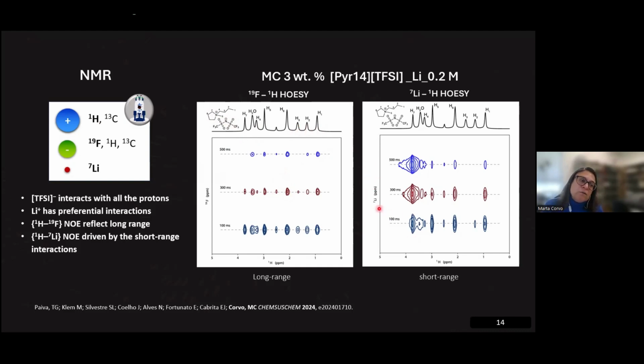And what is interesting is what we see when we look at the lithium-proton behavior, the lithium-proton correlations. Here you really are looking at some correlations that say the lithium is closer to some specific nuclei than to others. And this proximity, because these are more intense, larger correlations, means that the lithium is actually only seeing part of the cation, and these are short-range correlations. These short-range correlations are saying to us that although the anion and the cation are really, really close, lithium is not that much associated with the bis(trifluoromethanesulfonyl)imide in this case.